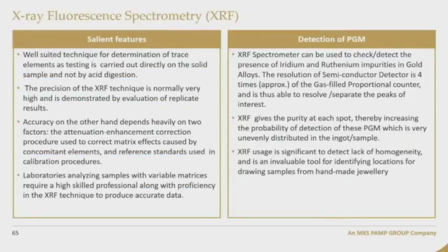Here are some salient features of XRF. It is a well-suited technique which we use for the detection of different elements present in solid samples. The precision of the XRF technique is normally very high, demonstrated by evaluation of replicate results. But the accuracy of the instrument depends heavily on two factors: the attenuation and enhancement correction procedure used for the matrix effects, and the concomitant elements, reference standards used for calibration, for the detection of certain impurities which you want to analyze. Laboratories analyzing samples with variable matrices use this machine for this detection. We also use this for the detection of PGMs.